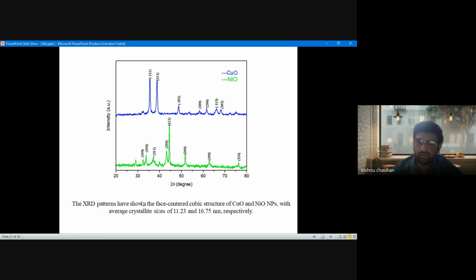How do we come to know? We have a standard data file, which we call JCPDS XRD data. This JCPDS XRD data is matched with our provided data. If all the peaks are well matched, we can say this is particularly of this structure. Here we can say we have the face-centered cubic structure of copper oxide and nickel oxide nanoparticles. On the basis of the FWHM and the intensity of the particular peak, we measure the crystallite size. We have the Scherrer formula to determine the crystallite size. So using that formula, we can determine the size of the nanoparticles.